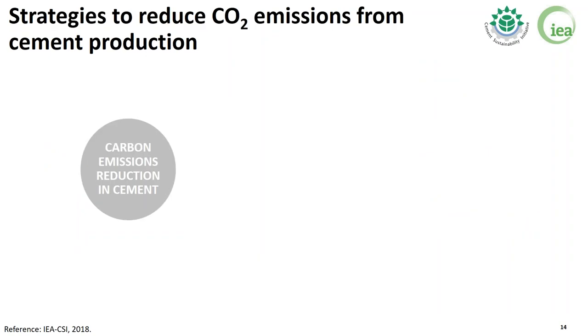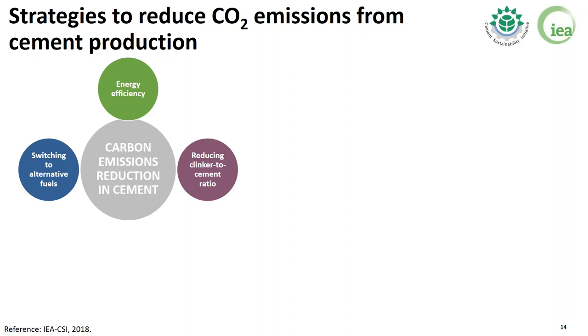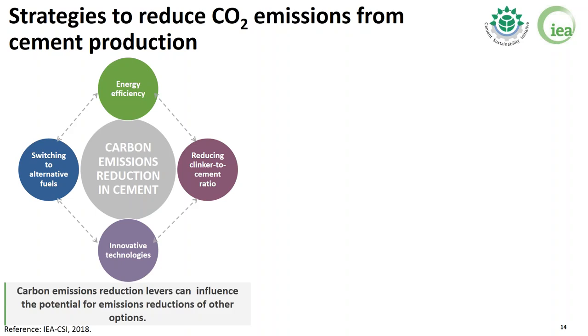So for the roadmap, we've looked at different sets of strategies for mitigating or reducing CO2 emissions from cement production, and we grouped them in four categories: energy efficiency, switching to alternative fuels, reducing clinker to cement ratio, and innovative technologies. Of course, all of them are interrelated in the sense that they cannot be explored independently. If you implement one of them, you may impact another one. For instance, if you switch to alternative fuels, for instance biomass or certain waste, then typically they have lower calorific content, which means that you may require greater thermal energy in the kiln. So this would impact, again, energy efficiency. And we've looked at those interrelations as well in the analysis.